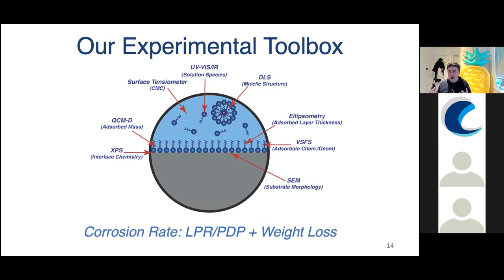And we have quite a large experimental toolbox to do this work. In terms of determining the corrosion rate, we use electrochemical measurements such as linear polarization resistance, LPR, or PDP, potentiodynamic polarization, to characterize what's going on electrochemically. And sometimes we also use weight loss measurements to complement the electrochemistry. Then, in tandem with that, to get this structure-performance relationship and build correlations between the two, we use a toolbox of characterization techniques, some of which are shown here. For instance, in the solution, we use a surface tensiometer to determine what's called the critical micelle concentration. And perhaps we're also using UV-Vis or infrared to look at solution species.